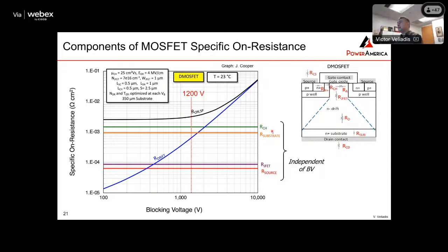Okay, as you can see, the channel resistance, the resistance of the substrate, the resistance of the JFET, as well as the resistance of the contacts is independent of the breakdown voltage. It's really the drift layer resistance, the resistance of this thick layer that holds the high voltage, that depends on the voltage, because as you go up in voltage, this layer needs to become thicker and lighter doped. And of course, another observation is that once you exceed about 3000 volts, the total resistance of your silicon carbide device is basically the resistance of the drift layer, right? You see how this total resistance starts to converge with the drift resistance.